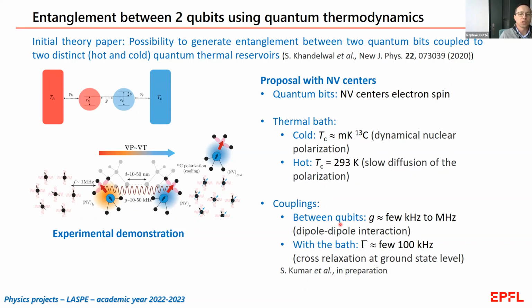Then the couplings which are involved in this problem are those occurring between the qubits. So the magnitude of the coupling would range between a few kilohertz and a megahertz, depending on the distance between the qubits. It is mediated by dipole-dipole interaction, and then you also have the coupling between the qubits and the bath, which is on the order of a few hundreds of kilohertz, which is mediated by cross-relaxation at the ground state level. So the paper is also in preparation regarding the theory adapted to NV centers.